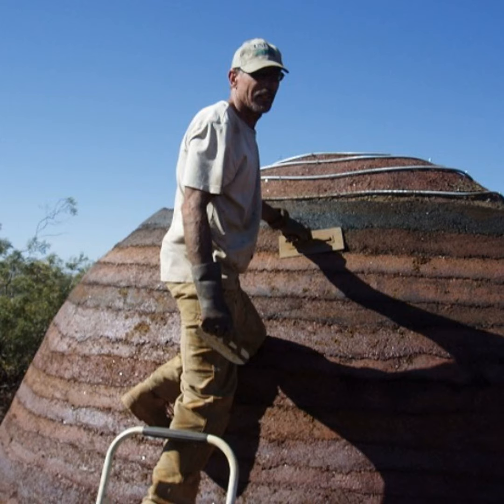It combines well with glass. It bonds tightly with glass. So we discovered that early on too. So out on the Native Nation, back to that, they had a glass problem. And they were 70 miles from the city of Tucson's landfill. So they had to collect glass and take it all the way into the city to dump it and then pay for that. So we combined Ferrock using EPA funding and combined the Ferrock with the glass to make our own concrete.